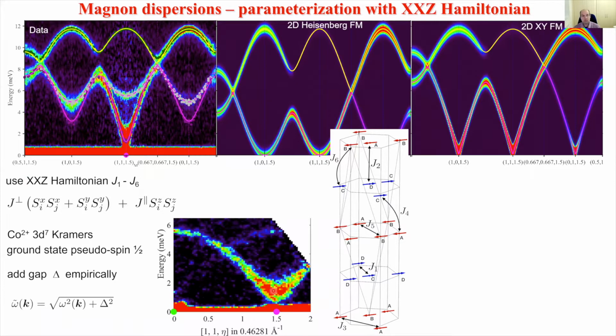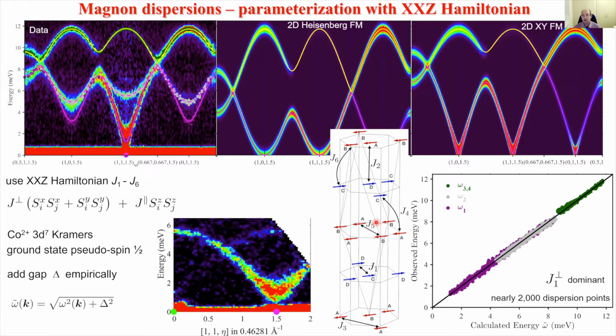That's not explained because within this model, this has full continuous rotational symmetry around the z-axis. The spins would always be able to rotate in the plane, and that would be gapless. So we add the gap by hand or empirically in quadrature to the dispersion relations that come from a Hamiltonian like this. And then including a number of further neighbor couplings up to the 6th nearest neighbor coupling,